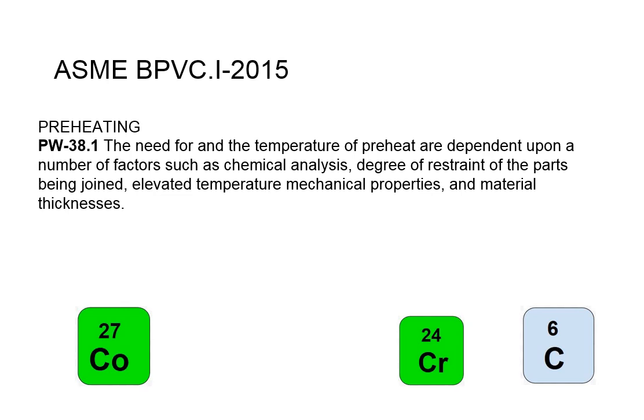In regards to preheat, are we welding something the size of sheet metal or half an inch thick? Or are we welding a material that's 7 inches thick? So with preheat, these are some things you really got to look at. Chemical analysis and material thickness are the two biggies that I generally gravitate towards. Not that the others aren't important, but the way my mind works, I go chemical analysis and material thickness, and then I look at the other information, kind of get my mind wrapped around it first, and then charge into restraint, and then what temperature this stuff is going to run at.